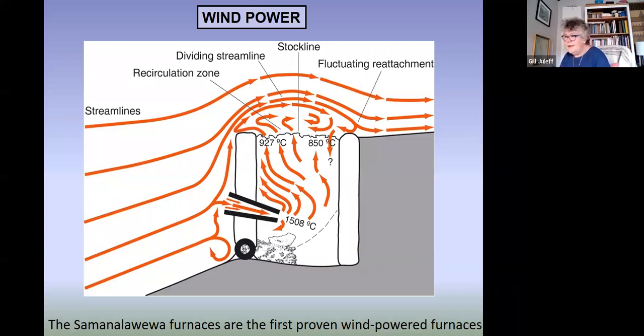Which is why that black line at the top of the front wall, this is a section through our furnace, is so prominent and so important, because it's that point at which the airflow divides and rises over the furnace and creates this internal recirculation zone. So this was our first interpretation of what we seem to be seeing in our experiments.